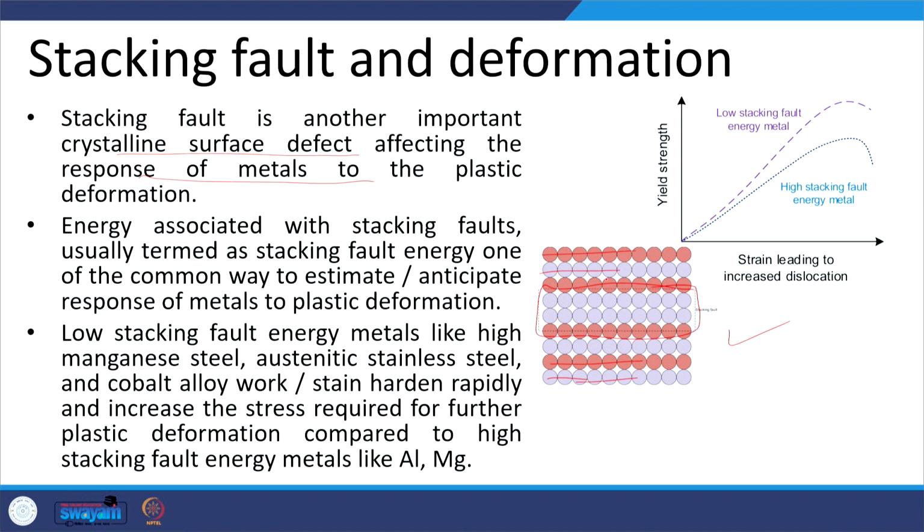So, this irregular arrangement of the atoms is termed the stacking fault, or the fault in stacking of the atoms. The energy associated with the stacking fault, usually termed the stacking fault energy, is one of the common ways to estimate or anticipate the response of the metal to deformation.